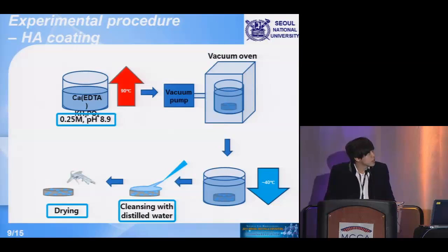And this is the procedure of the HA coating. We make the solution by dissolving calcium EDTA and potassium phosphate and heat the solution up to 90 degrees. After that, we put the porous magnesium inside the solution and also use vacuum pumping to put the solution inside the pores more easily. And after several hours, we take out the specimen and cleanse it with distilled water.